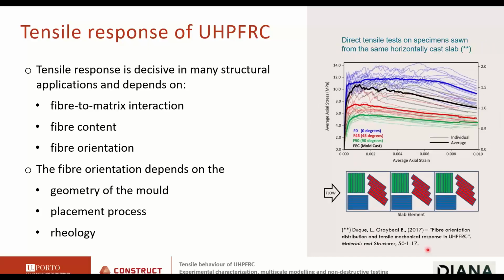Another evidence, taken from this reference here, where they cast a long panel of UHPFRC, but they let the material flow from this point over here at the left till the end. And then they cut longitudinal specimens to test under uniaxial tension, diagonal specimens, and transversal specimens. Here we should expect that the fibers are oriented in the horizontal direction. So the blue specimens are expected to show the best tensile behavior. And this is what we see here in the plot at the top.